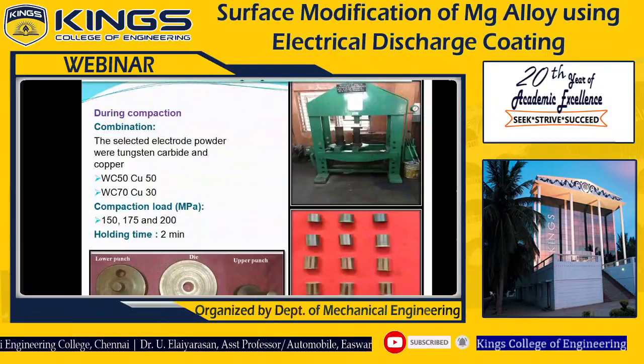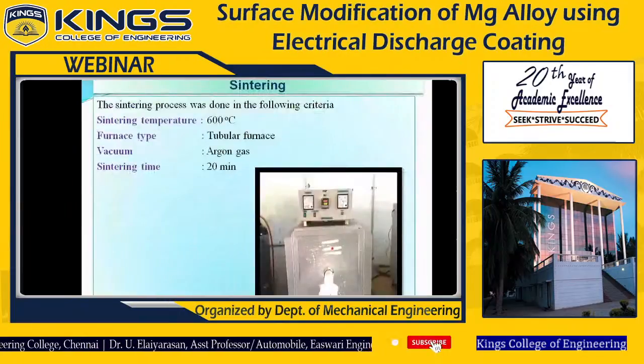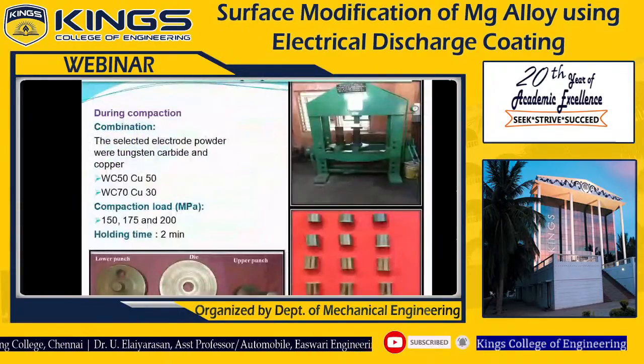The electrodes are prepared using different metal powders. During the compaction, different compaction loads are applied: 150 megapascal, 175 megapascal, and 200 megapascal. The holding time of the compaction is 2 minutes. Here I have given the manual hydraulic press. You can see in this slide, see the cursor movement, this manual hydraulic press with the highest load capacity of 50 tons, which is available in Annamalai University.